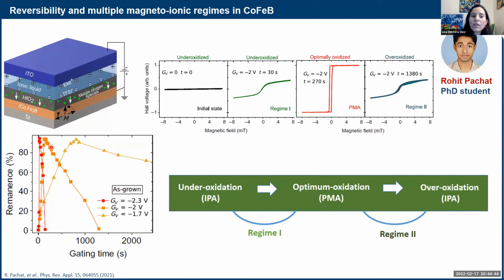But they really don't look the same in terms of dynamics. So it seems that the first one is a lot faster than the second one. In all cases, the second branch is much slower than the first one. So this is the first indication that something is different between regime 1 and regime 2. Although we're just adding oxygen into the system, we can see very well that it's a little bit more complex than we could have expected.